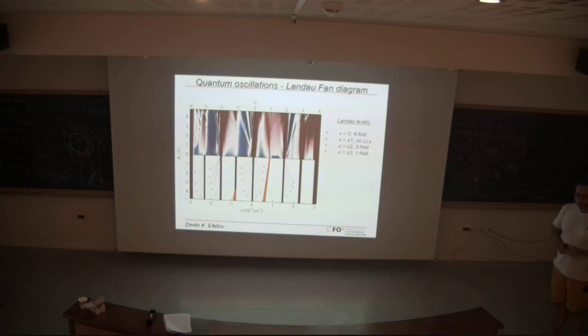What are the -2 and +2? We don't know. Okay. Why did you say... So again, for example, if it were a ferromagnetic state, you would expect a degeneracy of 2. But the weird thing is, we observe -2, +2, but then we don't observe the 2s to continue. This is highly debated right now, whether these plus and -2 could eventually mean that the underlying ground state is ferromagnetically ordered. So you could have, for example, here at the conduction band a spin up, and here a spin down ground state. But we don't observe any ferromagnetism here.